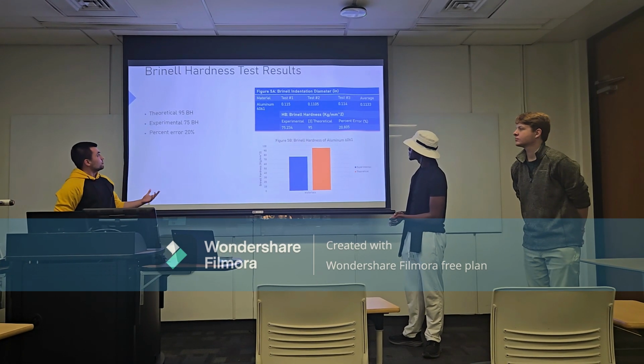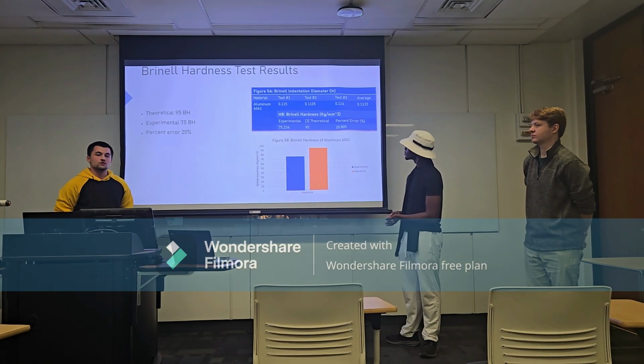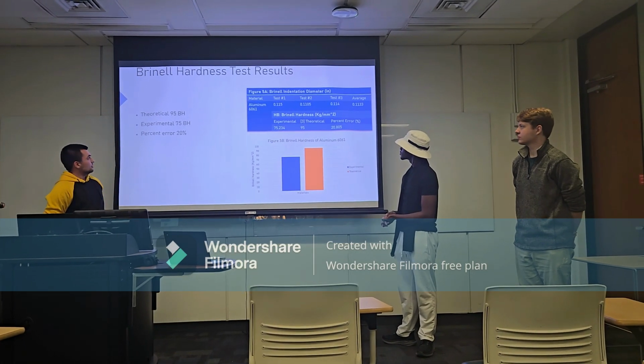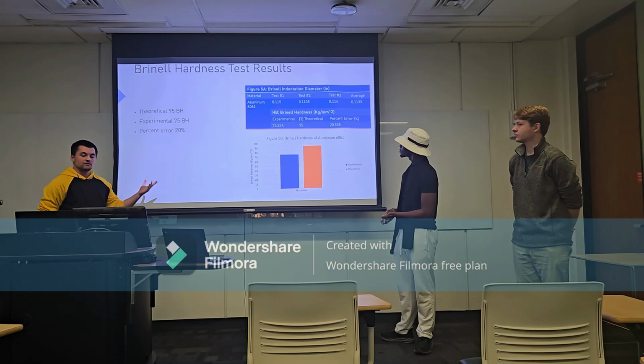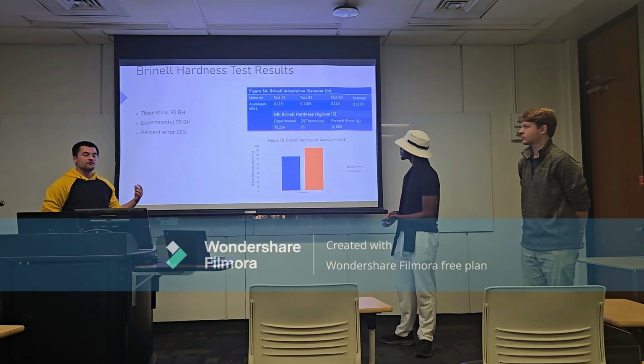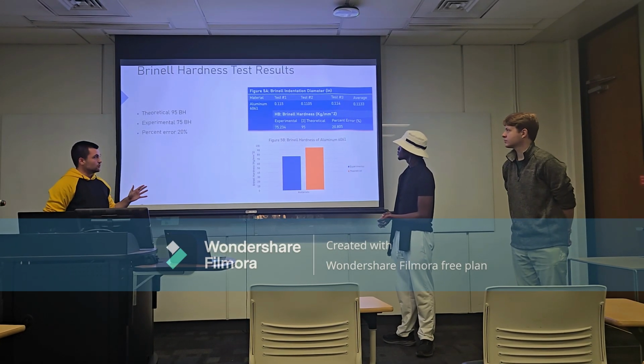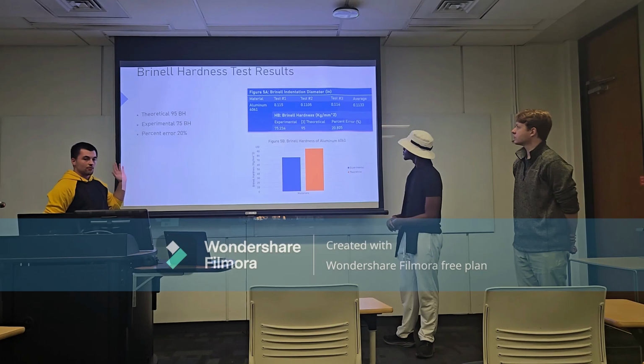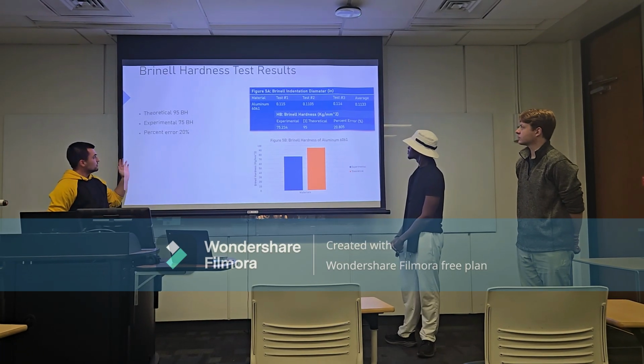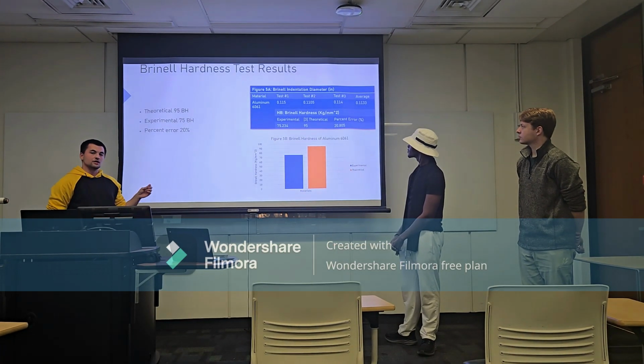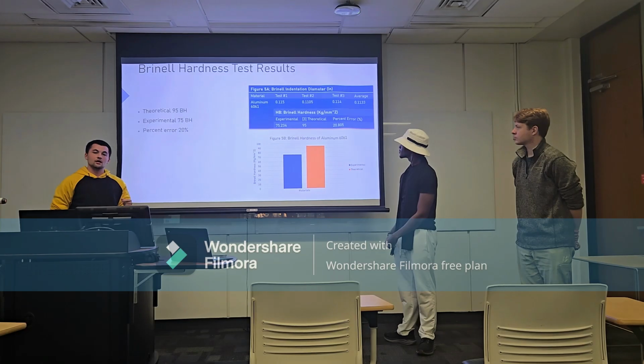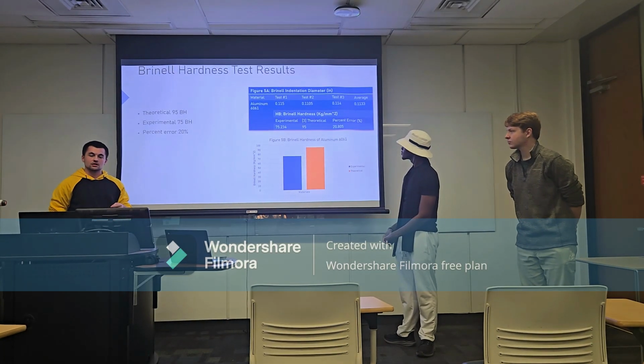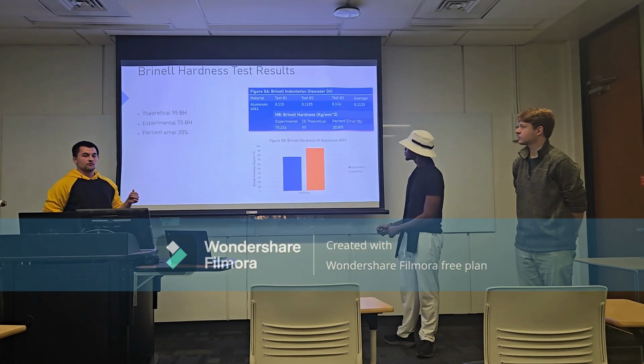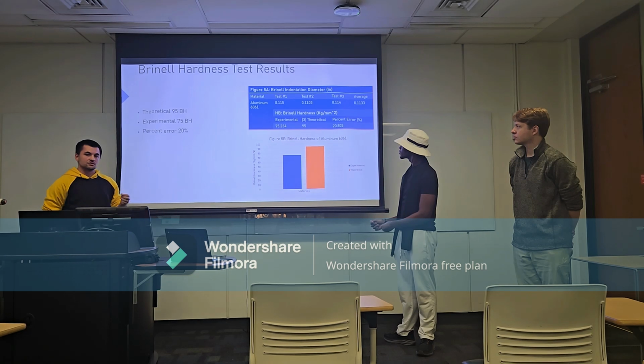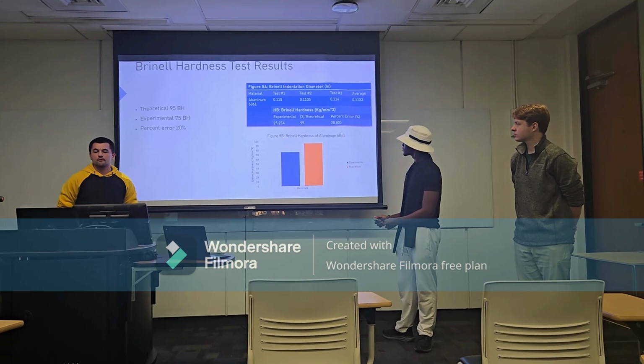When we used our Brinell hardness testing, we had to use a pneumatic machine, and we were given a 500 kilogram load on it, which would then give us our experimental value of 75, and because our theoretical, it being a 6061 T6 aluminum, should be 95, it gave us a percent error of 20%.